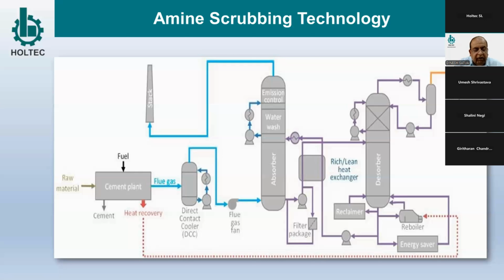So we go ahead with the gases which have CO2, of course, but no SOx, NOx, and dust. That will go to the absorption column. We call it the absorber. MEA will be flowing downward and the CO2-rich gas will be moving upward, so absorption takes place. The lean gas will pass from the top and be water washed so that no MEA is carried away and no other pollutants are going away. So we get lean gas out of the system through the stack, and the MEA which is rich in CO2 will now be further treated.